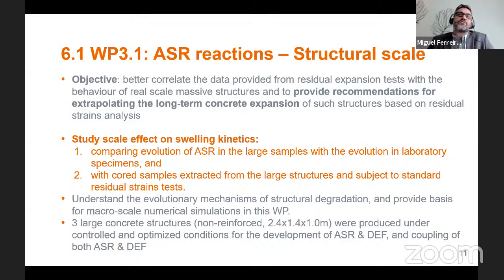So in this structural scale task, the idea was to better correlate the data provided from residual expansion tests. These are the ones made on cores with the actual performance of the structures. So the actual structures of concrete, yes. And to study the scale effect on the swelling kinetics, this is based on looking at the large block samples that have been prepared and cored samples which have been tested in the laboratory and measured to obtain residual strain tests. So how has this been taken forward?